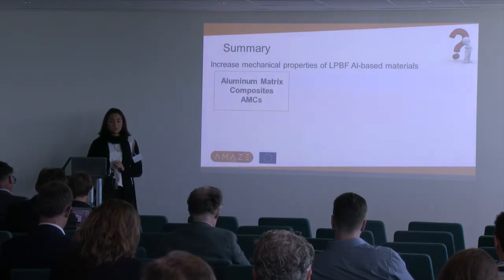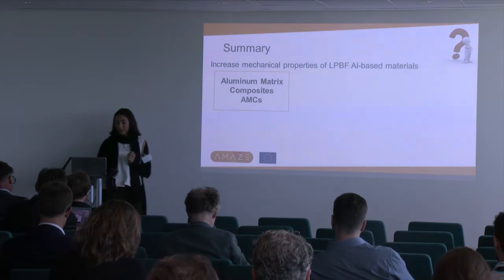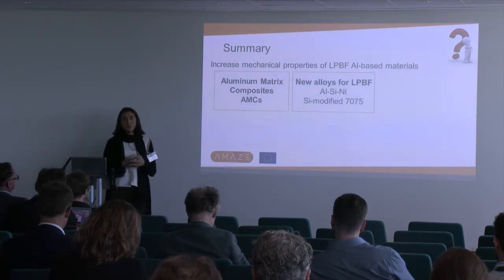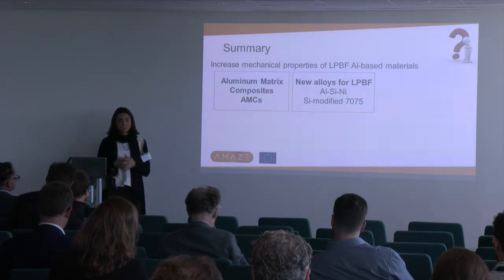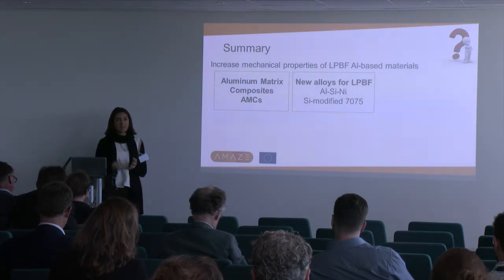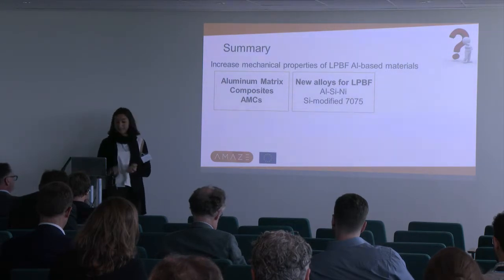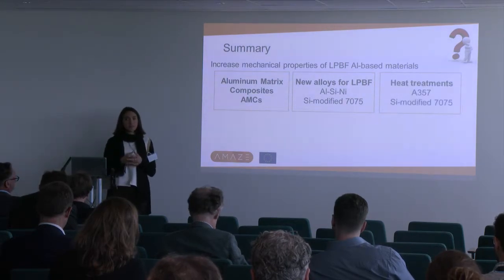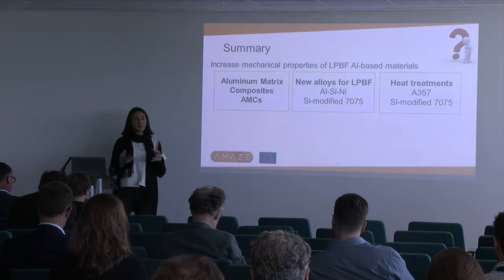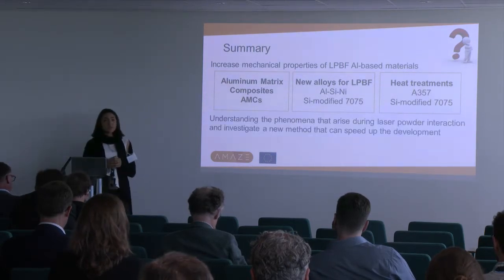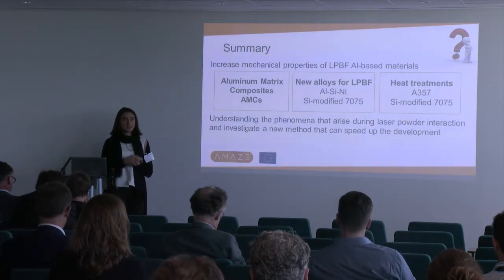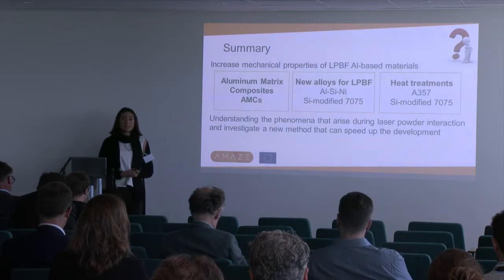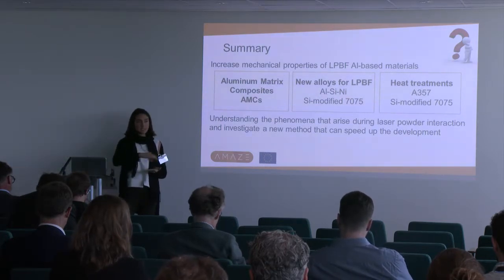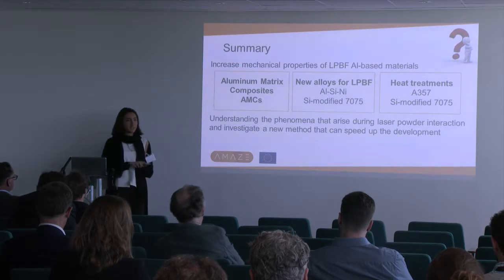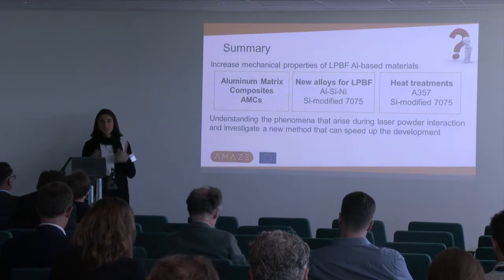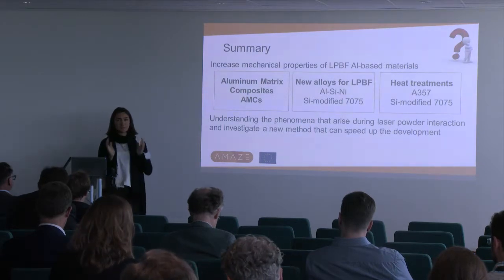So how to find new materials? At first we thought about building composites, then about producing new alloys which can take advantage of the fast cooling that arises during the laser scanning. And then we also focused on the heat treatment, so how to improve the microstructure of these alloys. Then we were also interested in understanding the interaction between the laser and the powder bed. And so we did some single scan track analysis, so a single laser scan on a powder bed, and we looked at the shape, the microstructure, and the properties of the single scan.